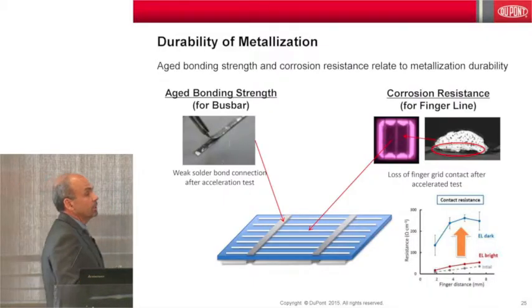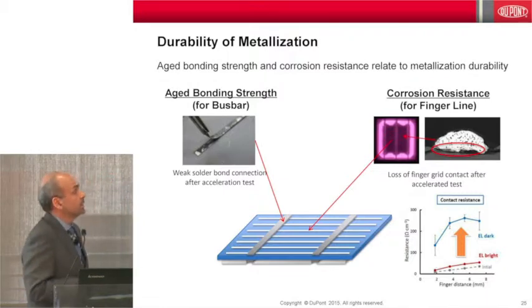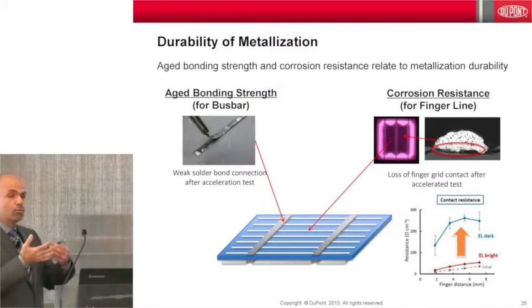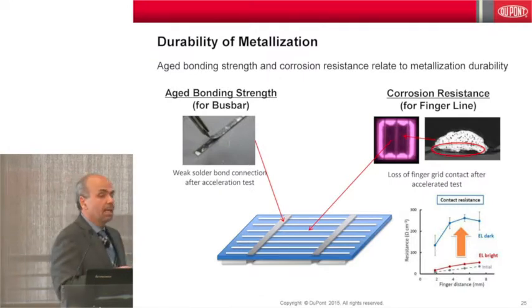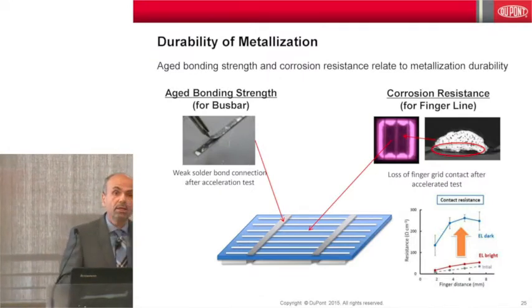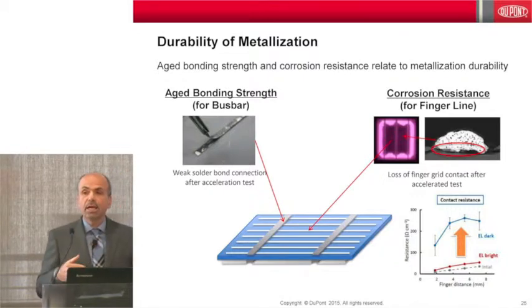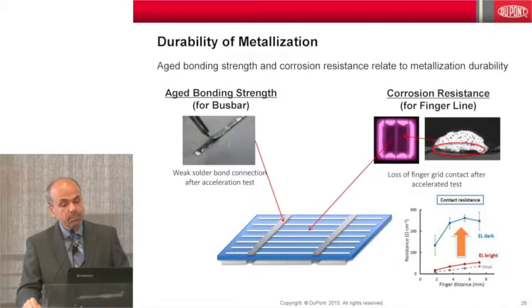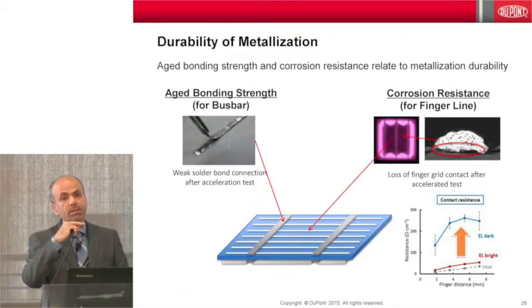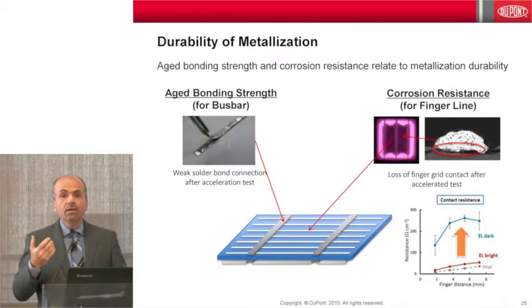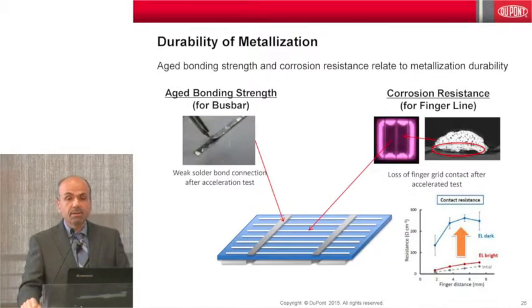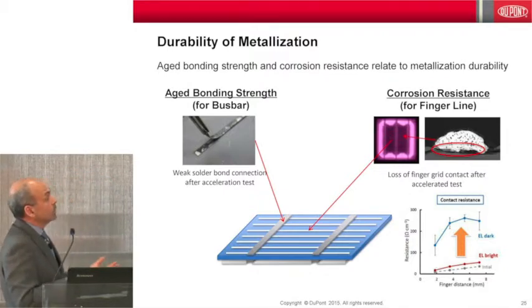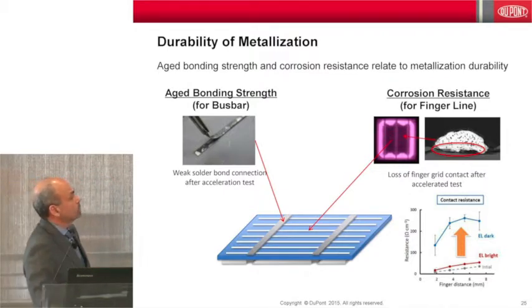The other area that we're looking into, and we're starting to interact with Stanford in this area, is to understand how the ribbons attach to the bus bars and how the metal fingers that I was talking about earlier perform under aggressive testing environments. It's very important to adhere the ribbons that collect the current very nicely on the cells, but at the same time, different environmental conditions can corrode the silver fingers, delaminate them, and eventually kill the device after prolonged exposure to different environmental conditions.